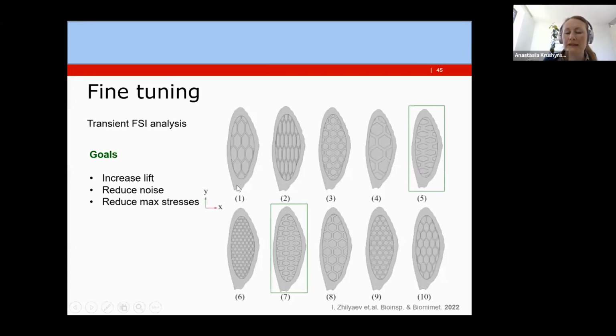Yeah, and it's also possible to cover the full surface of the wing by the pattern, but we do not do it. Why? Because we have these bounding vanes which allow us to preserve the structural rigidity. Basically, in the thinnest parts of the wing, there is just one printed layer, and if the pattern goes up to the end, the dynamics will be really not stable. So that's why we preserve the external vane, we call it like that, just to increase the structural rigidity at the edges. And then in the interior of the wing on the surface, we apply this still periodic pattern.